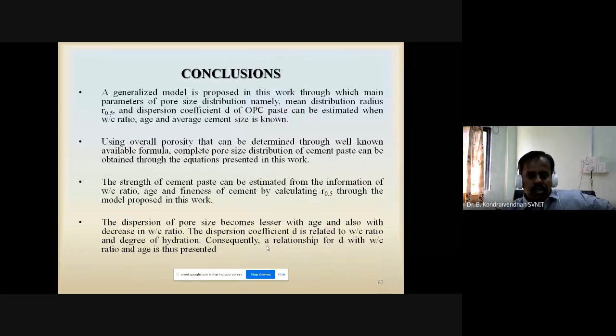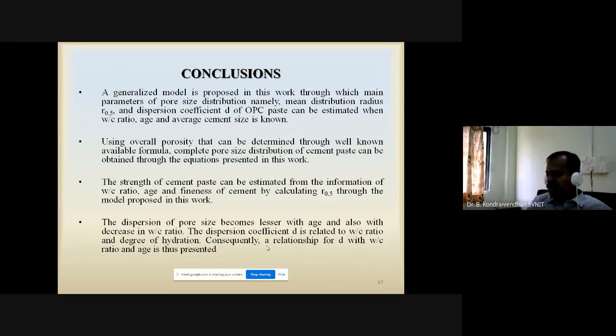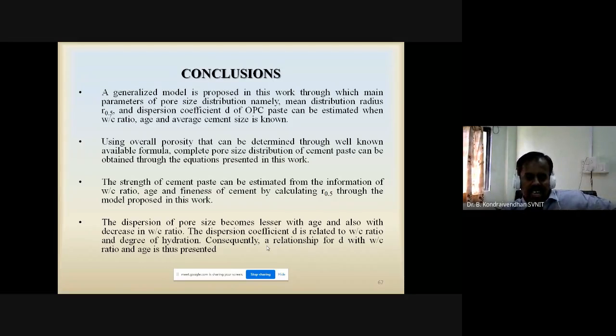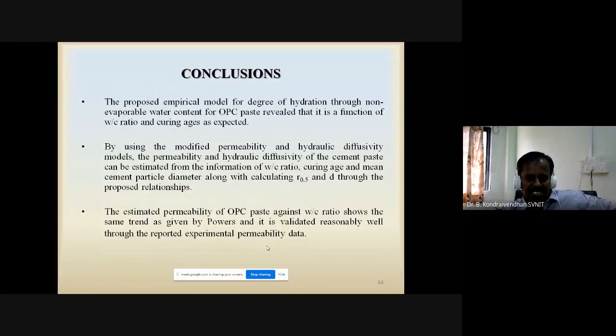From this, what I want to conclude is that it is possible to determine the pore size distribution parameters by using the water cement ratio, curing age, and mean cement particle diameter. Once you know the R0.5, D, and P, it is also possible to determine the compressive strength, permeability, and hydraulic diffusivity. And also, once you know the water cement ratio, curing age, and mean cement particle diameter, you can predict the degree of hydration. So all these things we have derived through our exercise. That's what I mentioned in the conclusion.